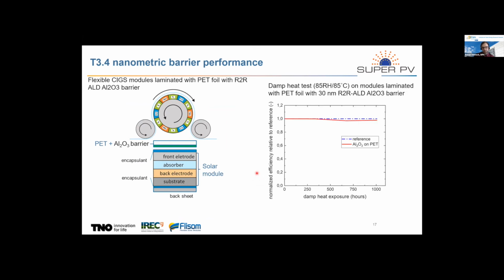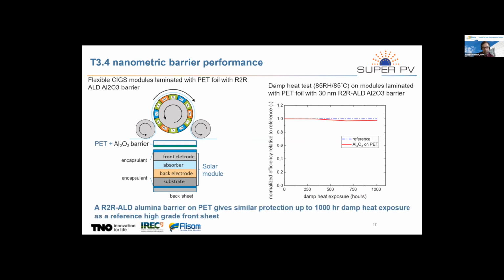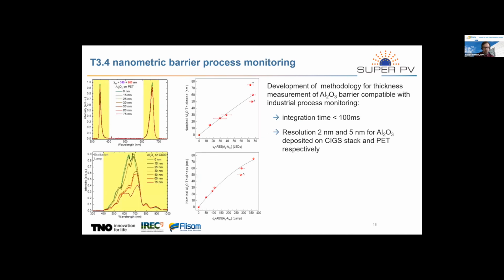And here we have some results comparing this innovation with the high-grade front sheet. Here we have the normalized efficiency of the module as a function of the damp heat hours. You can see here that the blue data is showing the reference, the red data is showing the aluminum oxide, and you can see that the degradation is less than 5%. The conclusion by TNO here is that this aluminum oxide layer on PET gives similar protection as this high-grade front sheet.